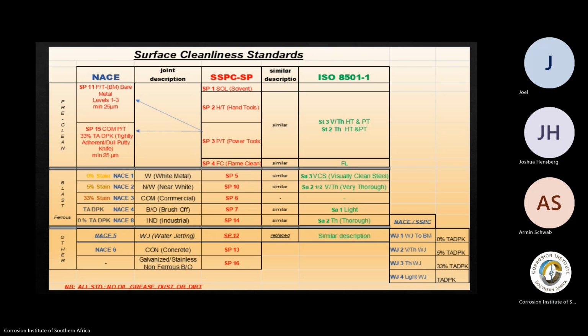Thank you very much. What is the time frame from finished blasting? It really depends on relative humidity and surface temperatures. If your relative humidity starts getting close to 85%, most coating suppliers will tell you if it gets to 85 or above, no coating takes place. Now the time frame shortens. If it's between 80 and 85%, you might have 1 hour to put a coating on. If it's between 75 and 80, you might have 2 hours. If it's lower than that, then they tell you 4 hours, 6 hours, or whatever.